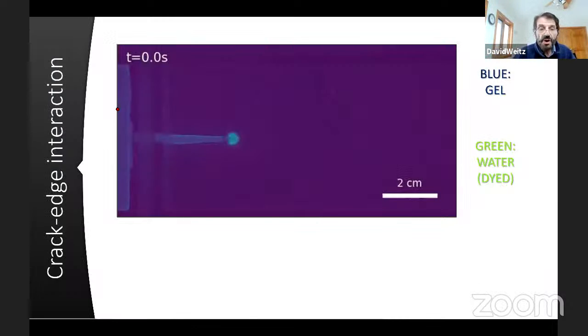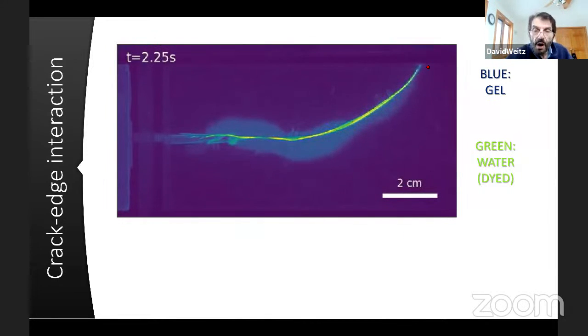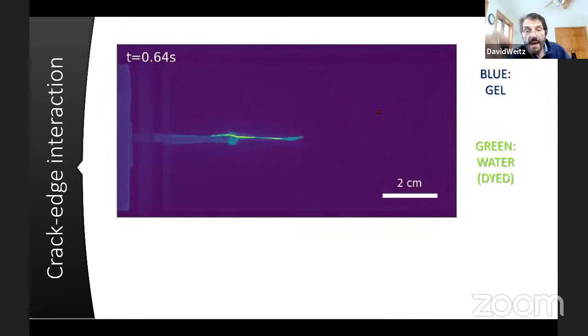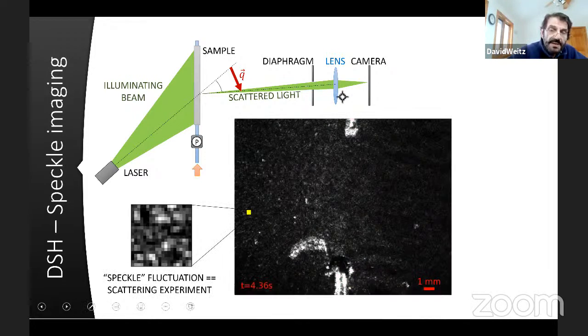Let's look at the behavior when you're doing something like one of these cracks. Here I'm going to show you what we're studying. This is the same thing, the colloidal gel. We're injecting, in this case, some dyed water. You see that a crack is forming. But now we're going to scatter from the sample over here. What we do is set up the laser so that we image the sample and collect the scattered light and image it through a diaphragm, so you get this speckle pattern. This is the speckle pattern, and this is a blow up of the speckle pattern.